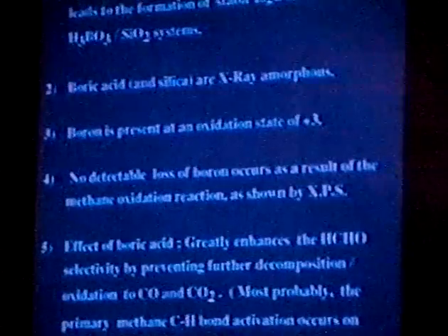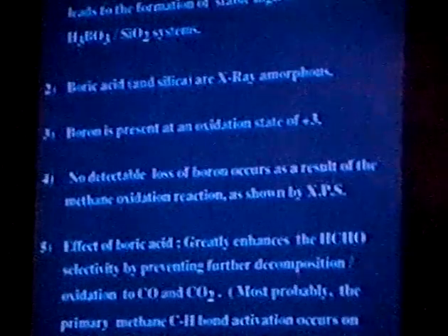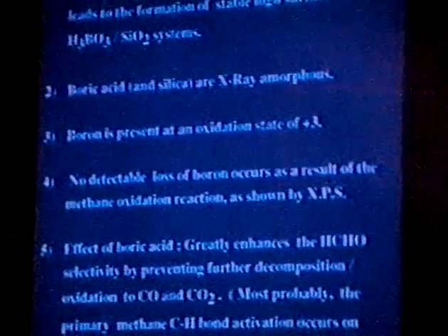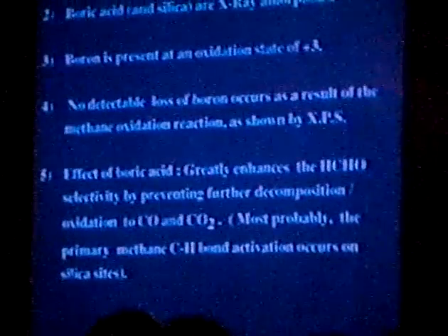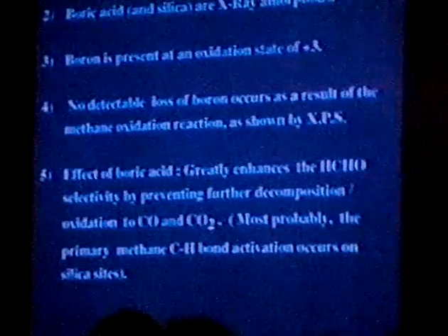We were particularly concerned about that because boric acid at the high temperatures used for methane oxidation is a liquid, but it seems that with this coagulation preparation method, boric acid is well stabilized in the Ludox. So finally, the effect of boric acid is to greatly enhance the formaldehyde selectivity and prevent further decomposition or oxidation of formaldehyde to carbon monoxide or carbon dioxide. Most probably, the primary methane (CH4) activation must be occurring on silica sites.